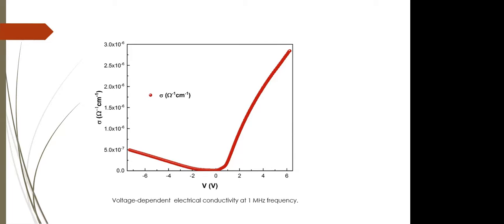Here, the decrease in the capacitance values and the increase in the conductance values in the accumulation region, or in other words, the decrease in the dielectric constant and the increase in the dielectric loss values indicate a conductive behavior of the sample in the accumulation region. That is, the minimum value of the capacitance in the accumulation region corresponds to the maximum value in the conductance in the accumulation region.